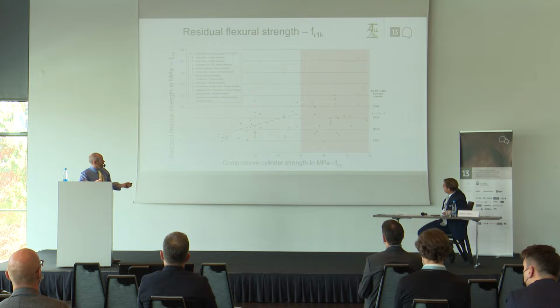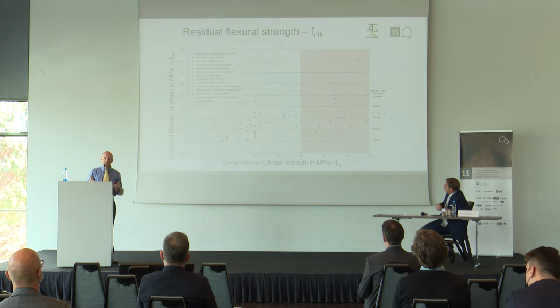One thing to note is the large scatter. So I'm presenting data here that's from beam tests, and that has been a problem with the test for reasons I can explain afterwards, that you can get quite a lot of scatter. So that gives us some idea of the strength at that level. But if that crack is opening, we need to know how ductile that behavior will be. Will it sort of come back up? Will it continue to go down? Will it drop in a brittle fashion?